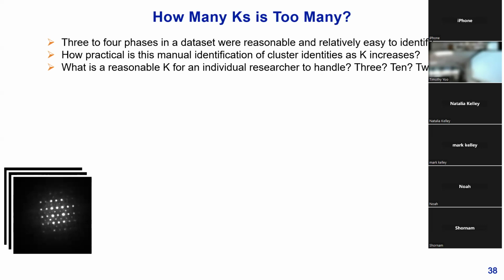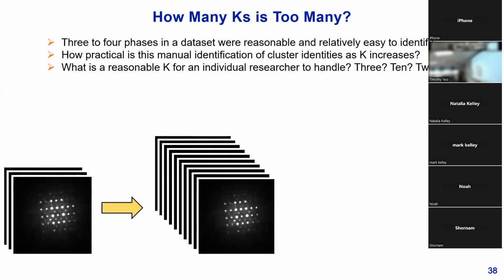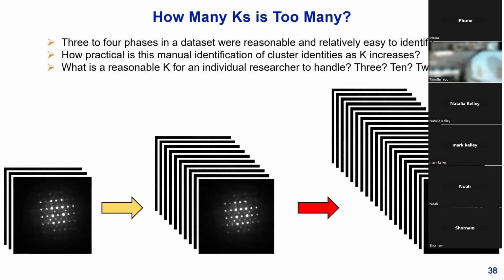Okay. But then when you start to get into systems with higher degrees of polycrystallinity, right, when that value of K starts to increase, at what point does it become too impractical for an individual person to try to identify? Because there's no guarantee that they're going to be aligned to a nice zone axis like this that can be properly indexed and identified, and then compared to simulations or whatnot. And so maybe 10 becomes reasonable, maybe that's the border region. When you get to 20, I think that's really pushing it. And so at this point, you ironically run into a big data problem again that becomes impractical for a single person to handle, which we were trying to address initially.